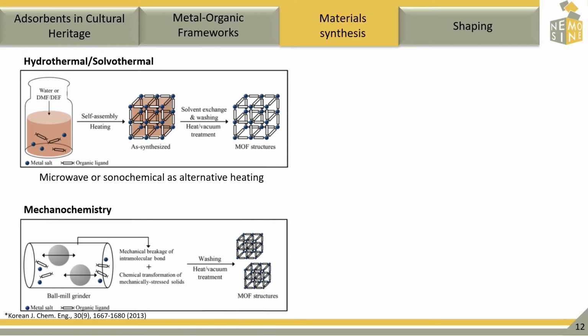Here, fluorinated benzene dicarboxylic acid and zirconium chloride are added to an autoclave with dimethylformamide, and the modulator, acetic acid, is added in order to decrease the reaction kinetics and help with the crystal formation. Then the autoclave is placed in an oven for 24 hours at a certain temperature.